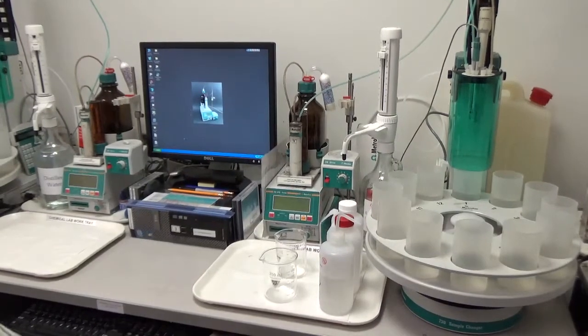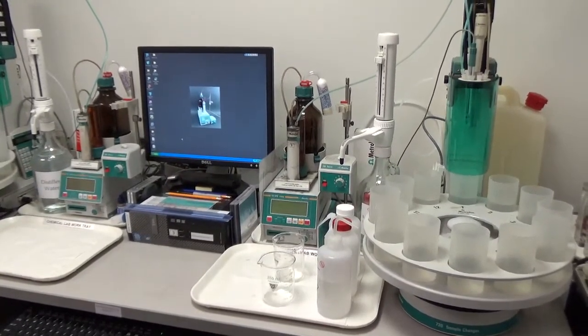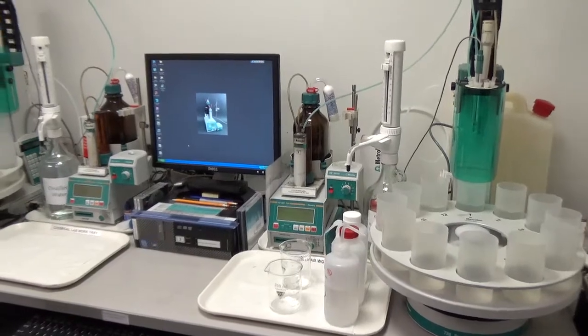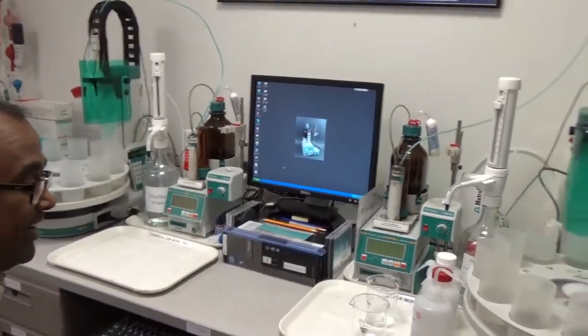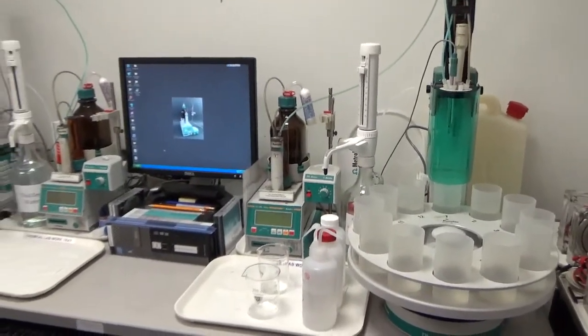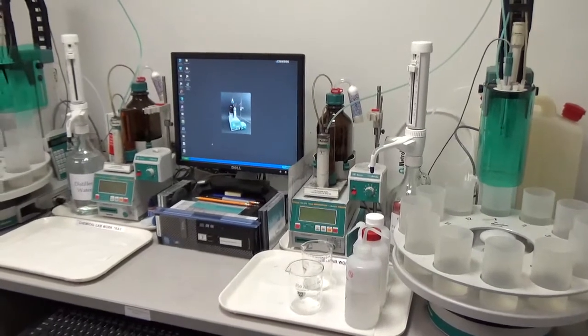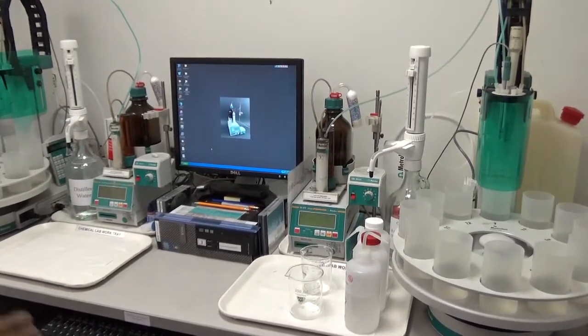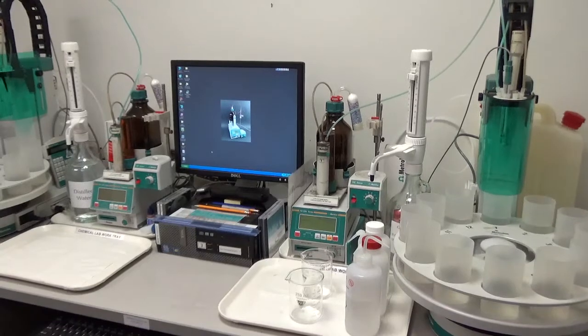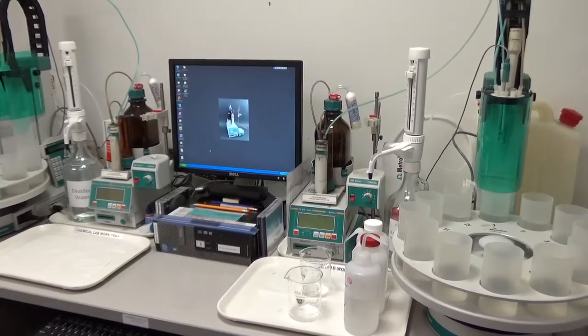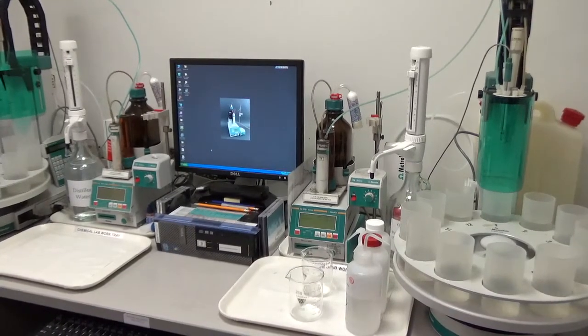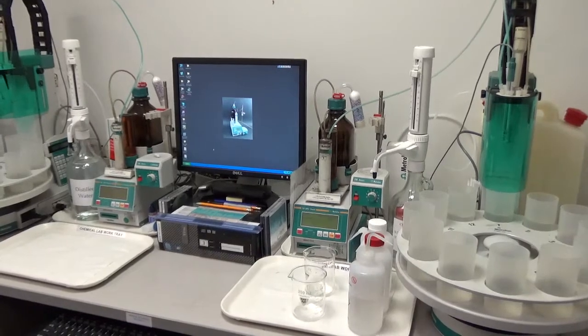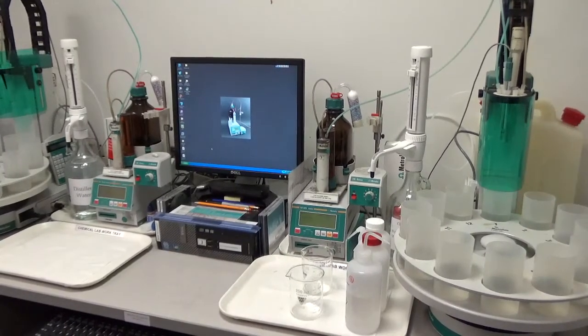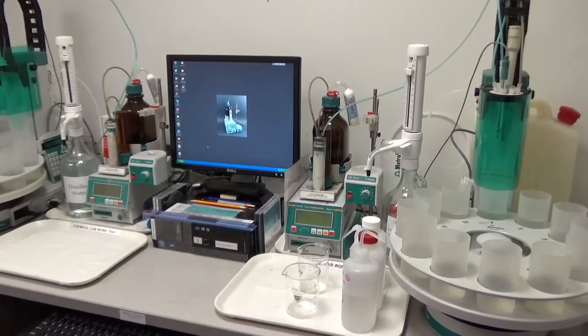Okay, so we have here two workstations set up to do chloride content analysis in concrete. We do both acid soluble chloride and water soluble chloride according to the procedures of ASTM C1218 for water soluble chloride and C1152 for acid soluble chloride.